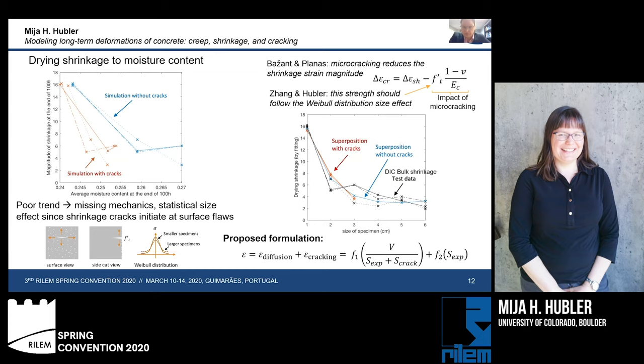It has previously been proposed by Bažant and Planas that microcracking reduces the shrinkage strain magnitude. So here this equation on the right shows the cracking strain should be the shrinkage strain without cracks minus the impact of the microcracking. Now if we introduce the Weibull distribution for a size effect with this tensile strength in here and the impact of the microcracking, we find that our drying shrinkage plot data can collapse onto a plot in terms of the size of the specimen.